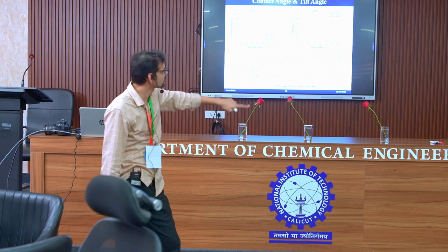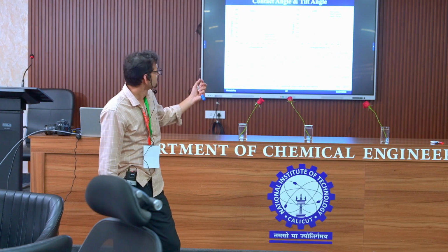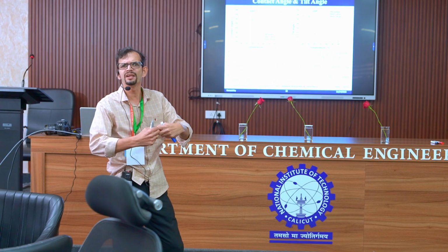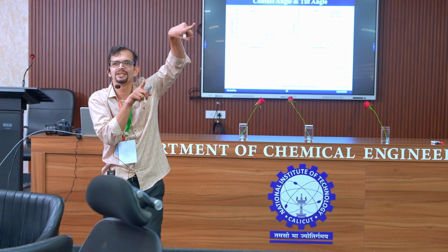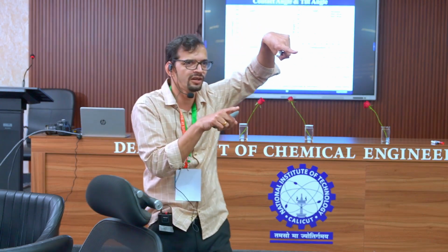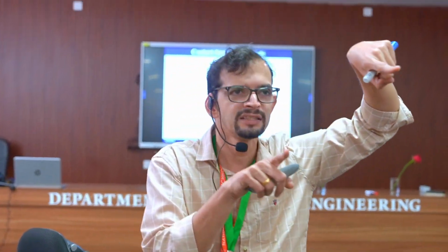And when it goes to the other temperature, the hysteresis is becoming near to zero. It's amazing, right? And you have a transition region. This is what we actually have the control. In a 2 to 3 degrees transition region, we can really work, because the region well below the transition and well after the transition is not useful for us, right? Because there is no gradient, right?